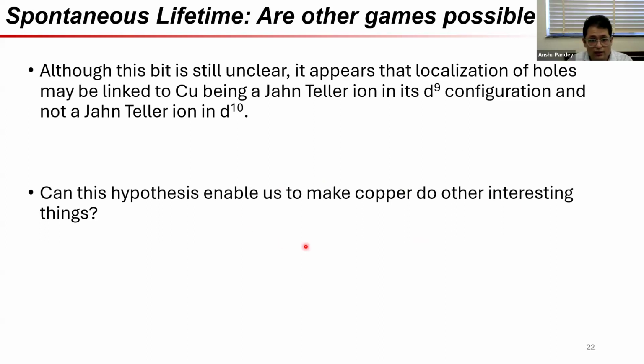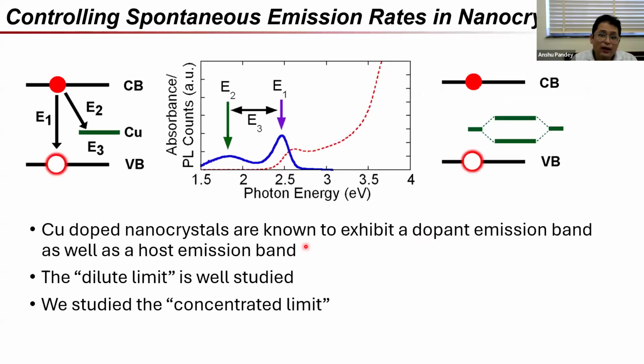So we did try to answer it. And certainly when we say interesting things, and our talk is mainly about spontaneous lifetime, we will talk only about that. So what we decided to do was actually look at copper, not just in the dilute limit, which is rather well studied, but actually move on towards the concentrated limit. So what is studied most often is when you add copper into, say, a well-behaved 2-6 material like cadmium selenide, it introduces a state over here, which is an atom-like state, and a conduction band electron can transition into that state.